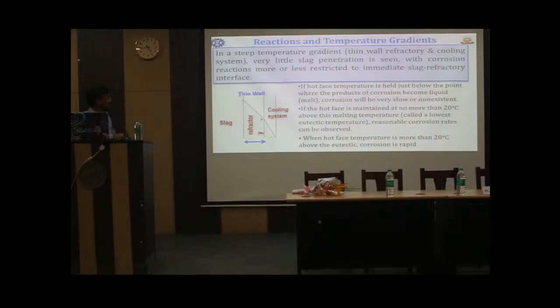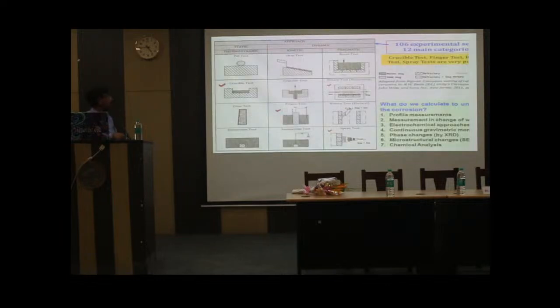So if the hot face temperature is held just below the point where the product of the corrosion becomes liquid, the corrosion will be very low because it will not penetrate. And if the hot face is maintained at no more than 20 degrees centigrade above the melting point, called the lowest eutectic temperature, there will be a reasonable corrosion. But if the temperature is more than 20 degrees centigrade above the eutectic temperature, the corrosion rate will be much, much higher.